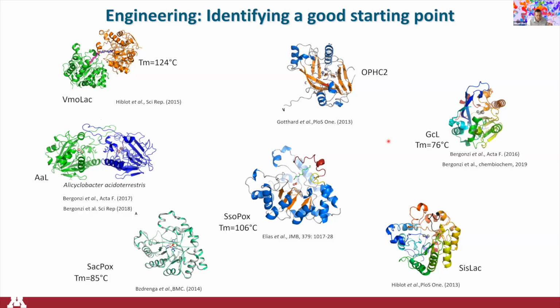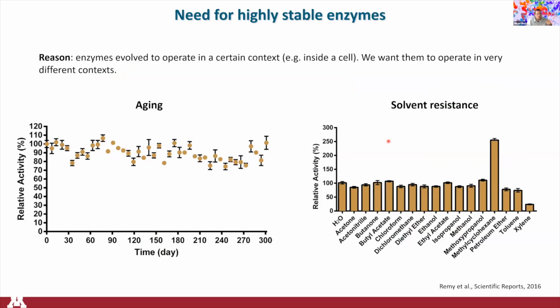And those are some of the enzymes that we initially identified and characterized, and we picked two because they have great stability properties and other aspects that were really appealing, and we further worked with those. Now, characterizing these enzymes, we realized that they have really interesting properties that are induced by their very high stability. That's why we selected them. But they have very interesting properties in the sense that they are fairly durable. So here you can see this is the enzyme activity, so its ability to degrade those signaling molecules over time. This is over 300 days in liquid conditions, so you can see that the activity remains fairly stable over the course of nearly a year, about 10 months.